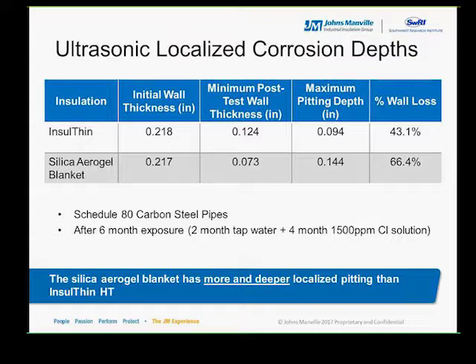If we do the math again as we did earlier, in the third column we see that the maximum pitting depth of the Insulthin sample is lower than the silica aerogel blanket. And what this means is that the Insulthin blanket, or the sample, has more metal remaining after the test period. Taking it a step further, what this really shows is that not only is the mean corrosion depth higher for the silica aerogel blanket, as calculated by the electrochemical method, but more importantly, the ultrasonic method can really see the presence of the critical deep pitting that can lead to failures. And it's really these localized pits that are the areas of most concern because they're harder to detect and usually where the failures occur.